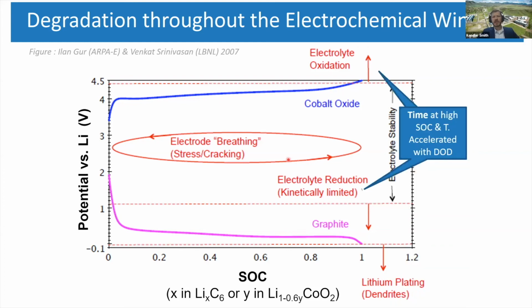And so just to observe how some of these different things track versus calendar time versus number of cycles, it's important to separate the calendar time influence and number of cycles influence if you want to extrapolate accelerated tests out to, say, a 10-year lifetime. These side reactions occur with calendar time. They're accelerated with high temperature and high state of charge. We also see that they are somewhat coupled with cycling, that if you deeply discharge a battery or sometimes operate at high C rates, what we feel is going on is that it either disturbs the SEI layer or it increases the surface area of the electrode and accelerates these side reactions.